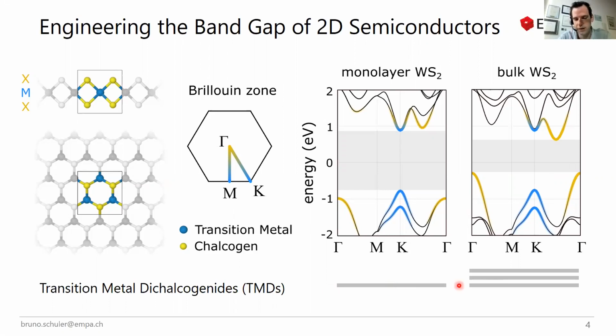Now, if you go down to only a single layer, a few things change. First of all, the band gap gets quite a bit bigger. It becomes a direct band gap as well. And the contribution to these extrema states is mainly composed of d electrons of the transition metal, states which have a high orbital momentum, and for this reason spin orbit coupling becomes much more important. There has been a lot of excitement about these materials, especially in the optical community. Because of this strong spin orbit coupling, it is possible to address different types of your Brillouin zone, for instance, the K or K prime point, by selecting the helicity of your incoming photon. So the spin and the valley degrees of freedom are coupled to each other.